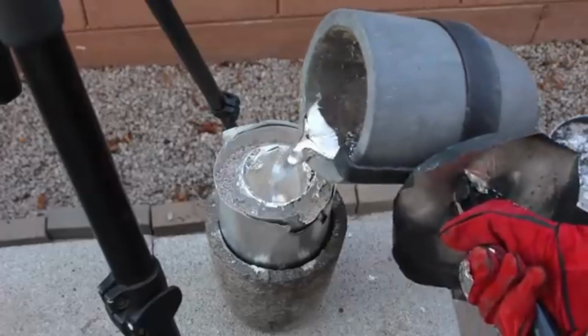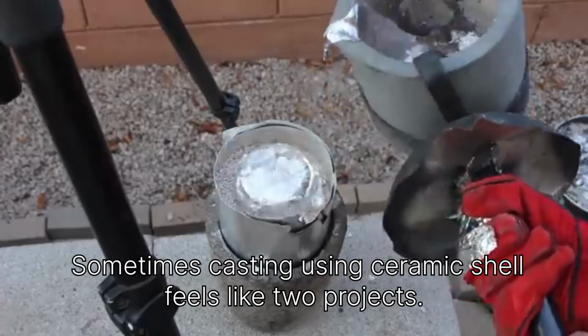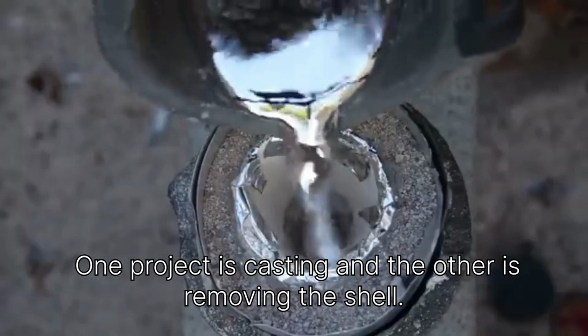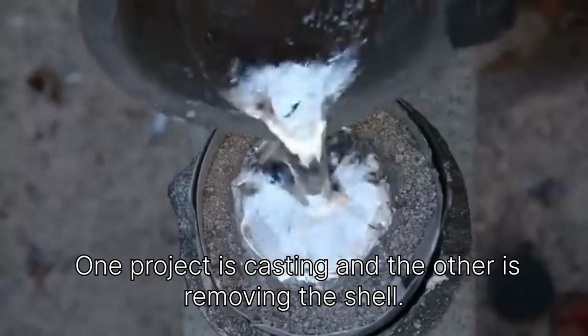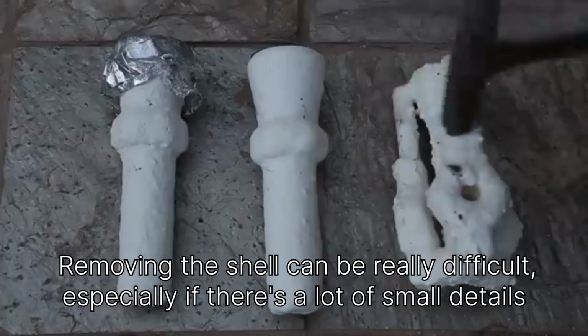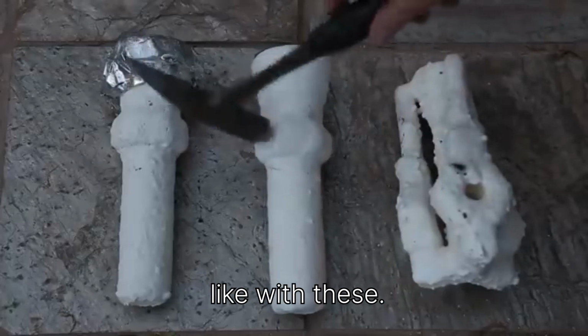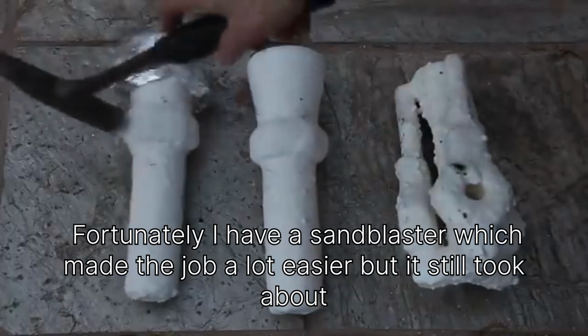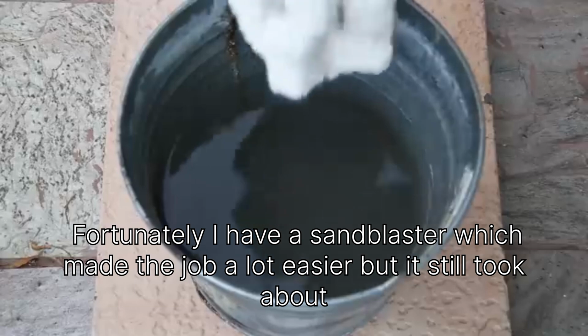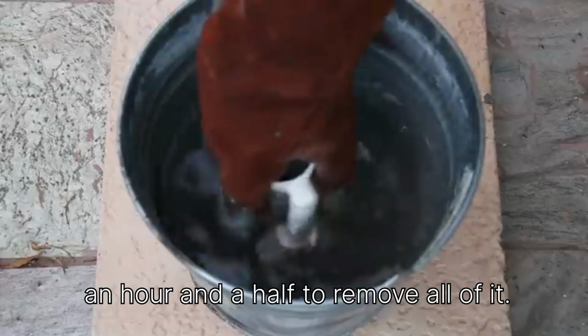Sometimes casting using ceramic shell feels like two projects. One project is casting, and the other is removing the shell. Removing the shell can be really difficult, especially if there's a lot of small details like with these. Fortunately, I have a sandblaster, which made the job a lot easier, but it still took about an hour and a half to remove all of it.